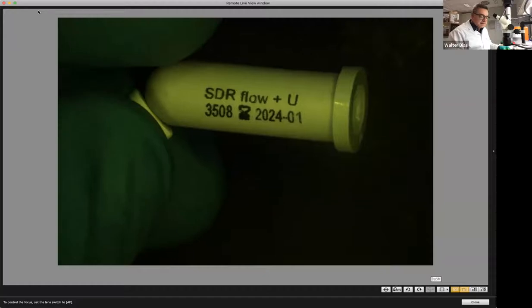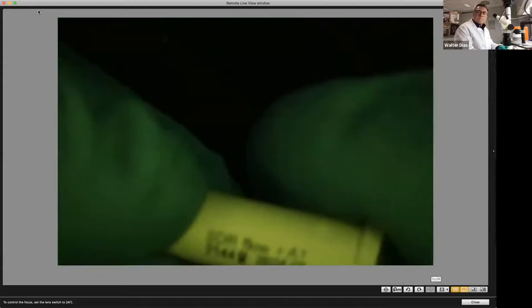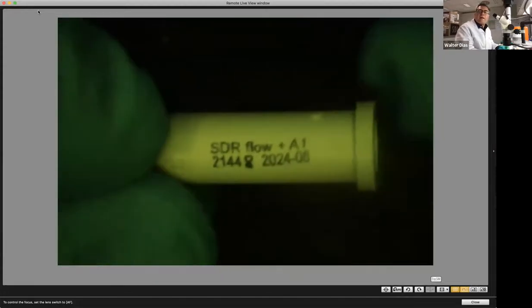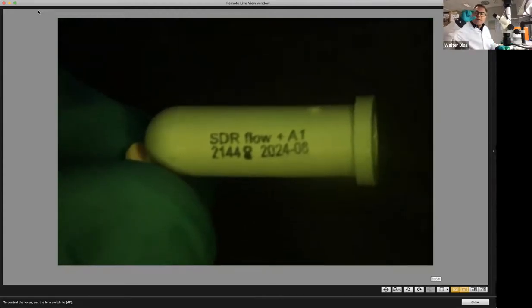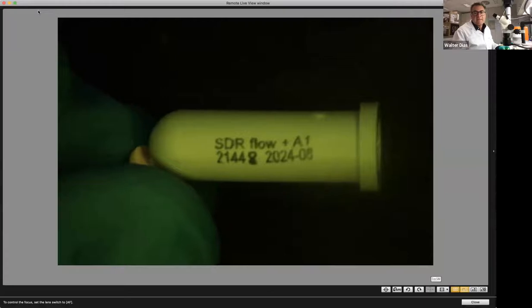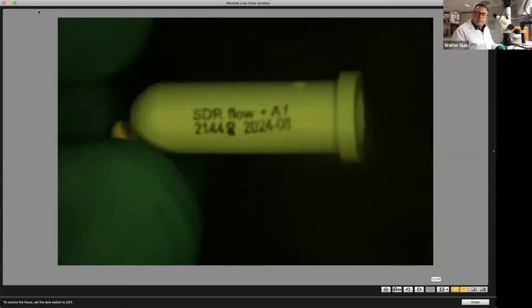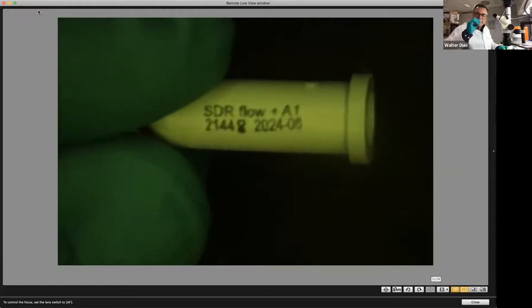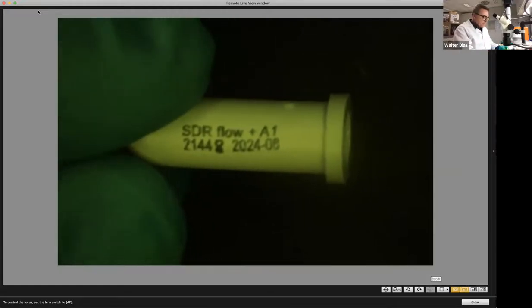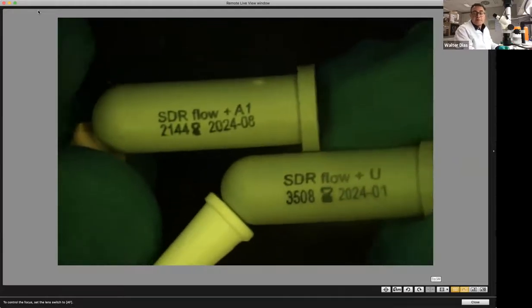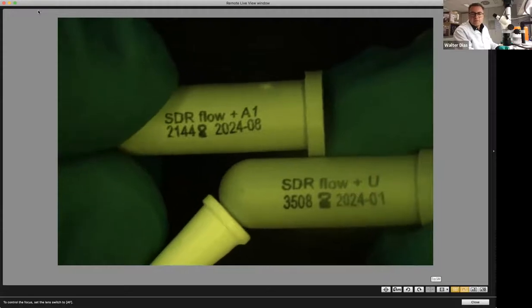It has very, very low shrinkage stress. It comes in different shades. I think I have a few other shades here. Yep, I have at least one. So this is A1. The difference is if you use the shaded one, if you use it thicker than 2 millimeters, then you need to cure it for 40 seconds. Yeah? But if you use this one in a layer thickness smaller than 2 millimeters, or if you use the universal, up to 4 millimeters, then the curing time is only 20 seconds. Only 20 seconds. So let me use the A1 because I'm going to use a very thin layer.